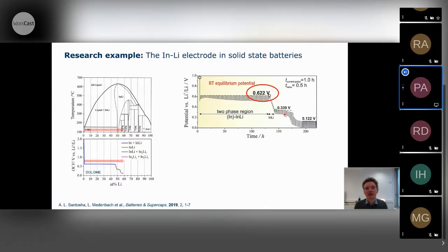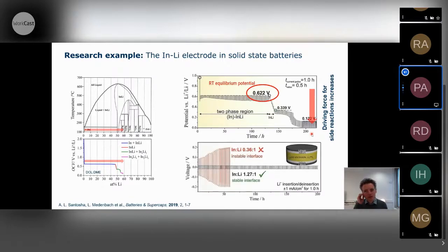And if you go too far, so if you assemble your counter electrode with too much lithium and too little indium, then you might end up here, and then your counter electrode has a much different voltage, even 0.1 volts. And then you get a wrong interpretation of your battery results. At the same time, the lower you go, the more the driving force for side reactions increases. And this is something that is quite important in solid-state battery research. If you have a bad interface with your anode, you get very poor performance. And this is just a slide that shows you when you are in the right region, so you only have, let's say, indium-1, lithium-1 as a counter electrode.